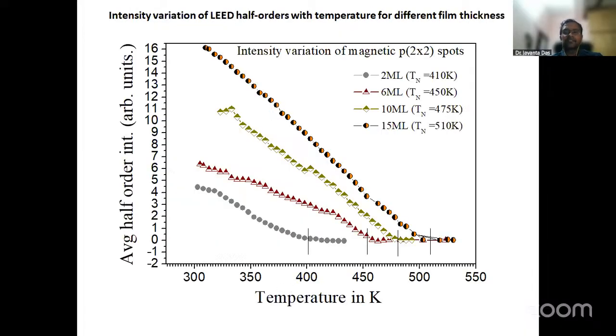Similar studies we did. The temperature dependent half-order intensity variation we studied for the case of 2, 6, 10 and 15 monolayer films, and this is the intensity variation with temperature, and we find that the intensity completely diminishes at different temperatures. So from 15 to 2 monolayers, we observed a gradual decrease of the Néel temperature of the sample.